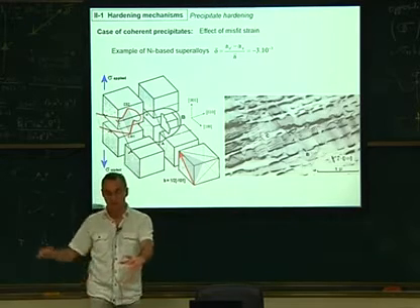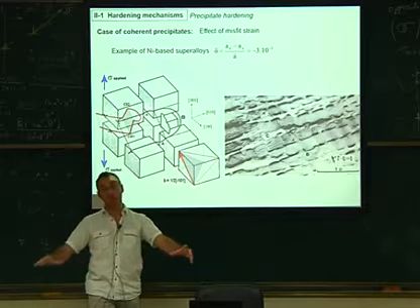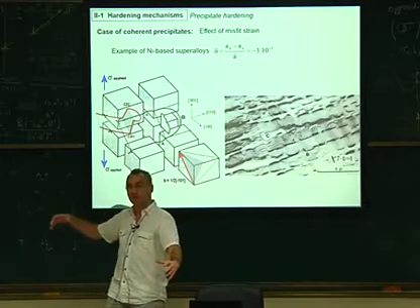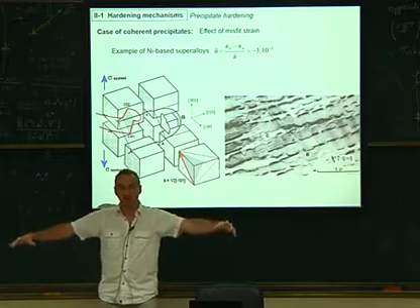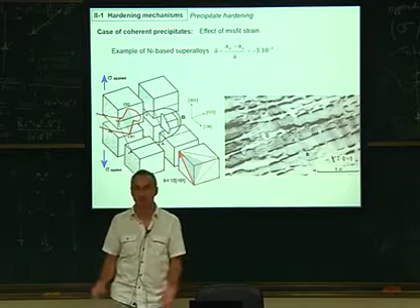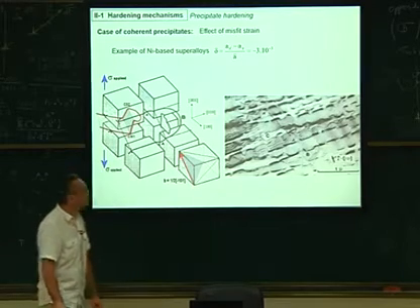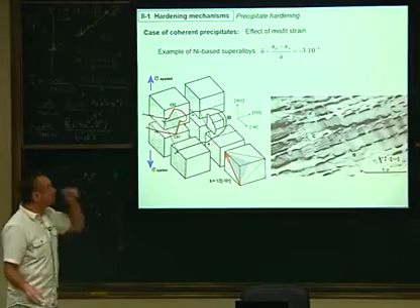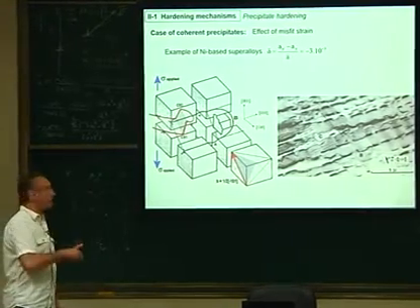And this, for the new incoming dislocation, could be seen as a big obstacle. For the first dislocation, it was just 2 obstacles. For the 10th dislocation, it's like a big one, so it's very hard for it to pass through. You see, that's the effect. So it's a collective effect on the hardening. So this was the idea of the internal stress field due to the Orowan loop.